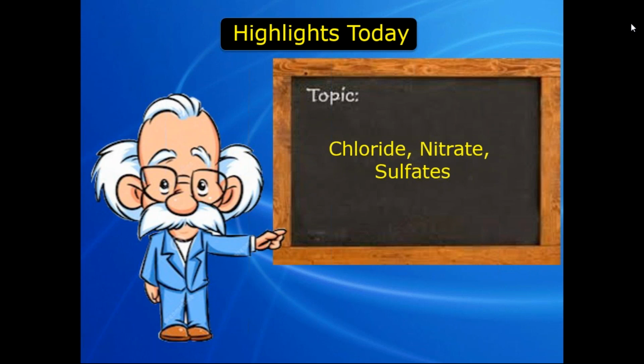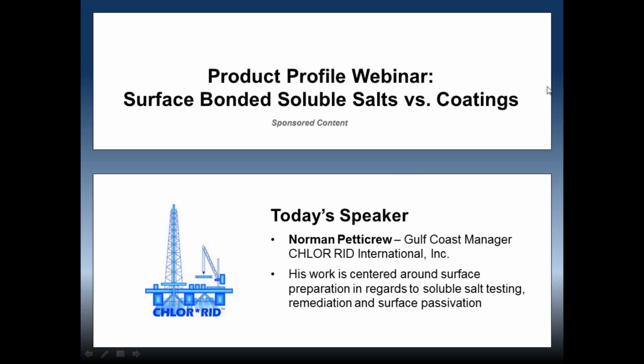All right, here's another application and tool question, similar to the one I asked a couple minutes ago. Is it possible to use an airless pump to wash the surface? I've done it a lot of times in the past, but you do need at least a minimum bulldog pump, a 30-to-1 pump, that will give you 3,000 psi at the tip, as long as you have a good tip that's in working order. And you need to make certain that the pump and the fluid hose are cleaned out to where there are no solvents involved. If there are solvents in there, you could have some other problems, but you just need to make certain that the lines are very clean.